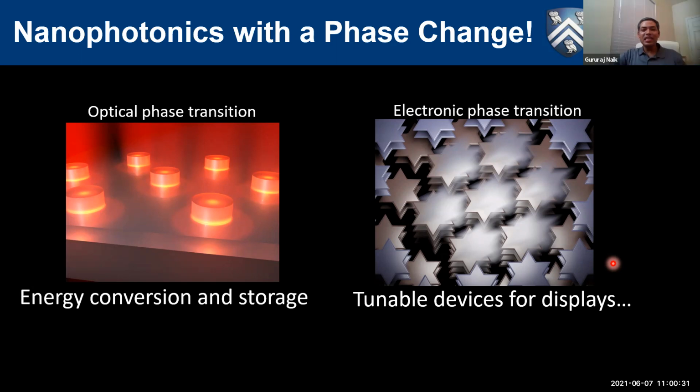Yes, yeah, that's again a very good question. We still don't know the answer. So what we did was we did 1 watt per centimeter square, and then after that, we actually did laser characterization where we had from 32, I think, watt per centimeter square to about 120 watt per centimeter square. So in all of this range, we did see tuning, but we also had very strong photothermal effects. So this material is also sensitive to temperature.